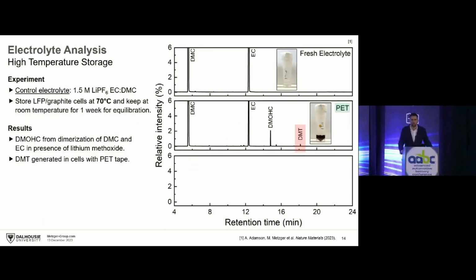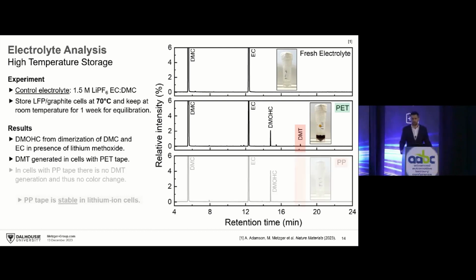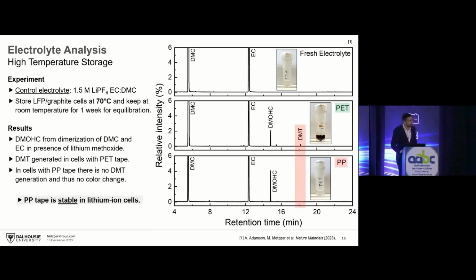So this is a high temperature storage test. If we have the PET tape, the electrolyte changes color, we get the DMT redox shuttle molecule in gas chromatography. But what if we change the tape? So here is a cell which has the polypropylene tape. Even though we stored the cell at 70 degrees Celsius for a long time, the electrolyte stays perfectly clear, and there is no DMT shuttle molecule that we detect in GCMS.